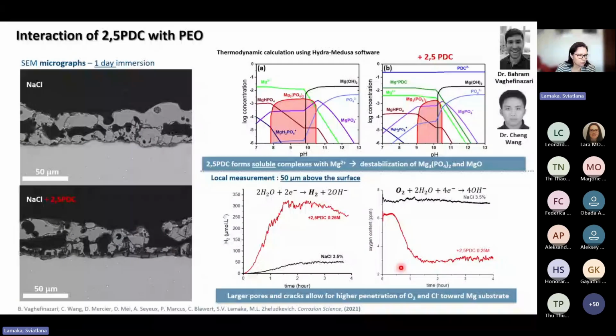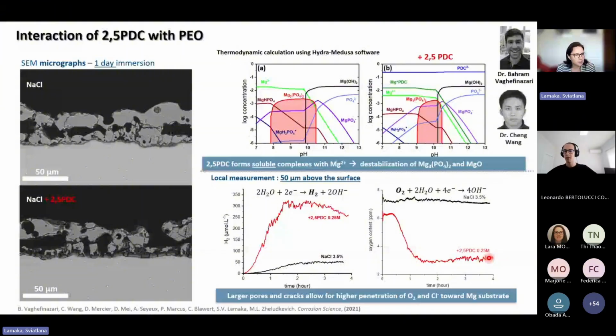And this was a very important conclusion for us, because we realized that inhibition effects observed for bare alloy cannot be taken for granted for PEO-treated alloys, and the compatibility of a PEO inhibitor needs to be validated case by case. So with this, I'm through my slides. I would like to highlight that microprobe techniques are extremely powerful and provide plenty of information about mechanistic details of corrosion processes.